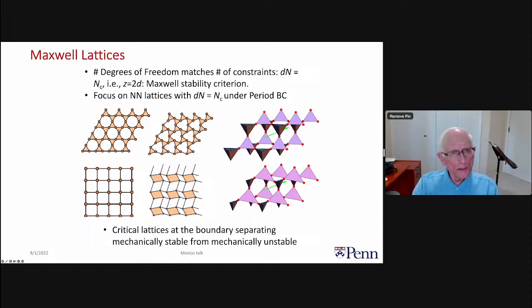Here you have a very interesting transition in the Kagome lattice, where you can rotate the triangles relative to each other in a uniform fashion. And that idea can be extended to pyrochlore lattices in 3 dimensions, such as shown here. This is the perfect pyrochlore lattice. Each red site has 3 degrees of freedom, and there are 6 bonds coming out, the 3 bonds on a tetrahedron. And then you can distort this. You can change the lengths and so forth. Nature doesn't do that for you, but you can construct an object like this in 3D printing or various other mechanisms. And when you go from here to here, the topological properties of the phonon spectrum actually change.